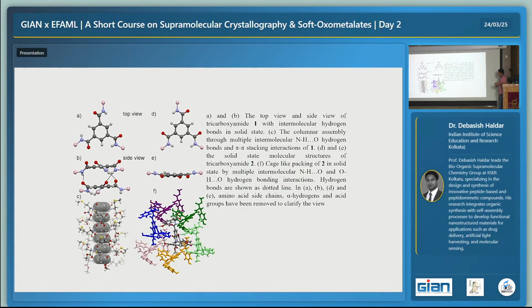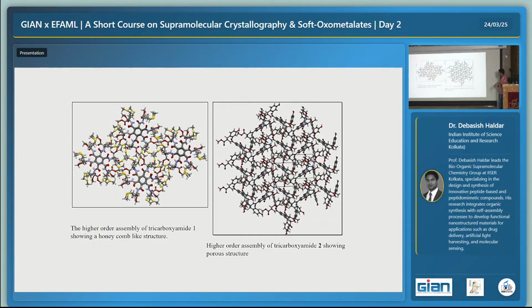Then we checked the central core area. When it is C3 symmetric, the amide bonds are actually perpendicular to the plane of the central benzene ring, and that helps a threefold intermolecular hydrogen bonding interaction, and finally it forms a columnar structure through intermolecular hydrogen bonding. But when it loses the C3 symmetry, the amide linkages are in the same plane as the benzene ring. Though there are multiple amide linkages, there is no intermolecular hydrogen bond between them. Rather, one molecule is now surrounded by 6 other molecules, and it forms a cage-like, porous structure. This is the packing diagram, which shows a honeycomb-like structure, and this is a porous structure.